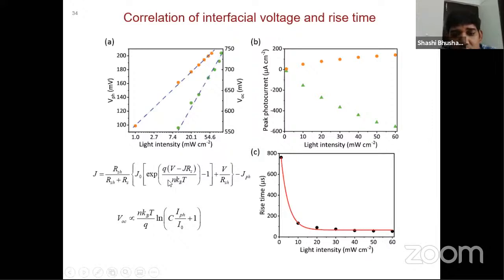Then we can compare the VPH, the photoelectrode voltage, with the open circuit voltage. Open circuit voltage is the fundamental of a solar cell, and this VPH photocurrent, which we measured with the electrophysiology setup, is the fundamental of our photoelectrode. Both have a linear relationship in the logarithmic plot, which shows that they follow one to one. So it also confirms that our photocurrent depends on the VOC behavior.